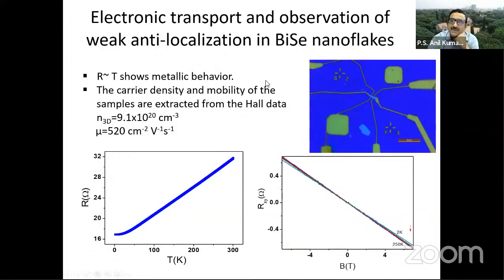Here, the first experiment, what we do is that you have a device like this. You measure the resistance of this sample as a function of temperature. And what we found was it shows a metallic nature. Ideally what I wanted was an insulating behavior, like we do with three-dimensional topological insulators, where we do compensation doping and we get an insulating behavior up to a certain temperature. And then we have these metallic surface states taking over.